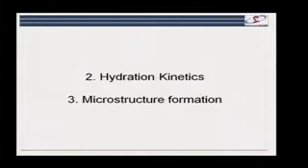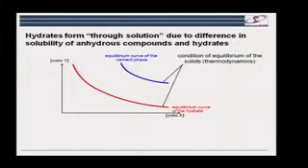So now let's talk a little bit about kinetics. Well, actually, I'm not going to talk much about kinetics, for reasons I'll explain. Okay, what's the basic mechanism of hydration? The basic mechanism of hydration is that things go into solution and then they reprecipitate. That seems quite a simple thing, but there was an awful lot of debate 100 years ago about whether this occurred or whether it was a solid-state reaction. You still read in a lot of textbooks that there are solid-state reactions. There are not solid-state reactions in cement because, not least, the crystal structures of the hydrates are totally different from the crystal structures of the anhydrous.